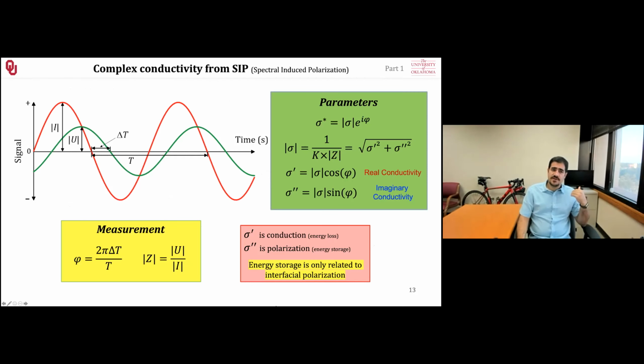What happens with the complex conductivity, or basically spectral induced polarization, because we're measuring the induced polarization over a range of frequencies, is that we are injecting the current at different frequencies. In here, just one frequency is shown, right? And what it causes is the ions to become polarized. Now, as this current is changing its polarity, the ions tend to get redistributed. And because ions take time to get redistributed, we will see something called a phase lag. This time difference gives us the phase lag. Basically, when measuring the potential, we will see everything with a time difference. We know the current that we injected, how much amperage we injected, and how much voltage that was.